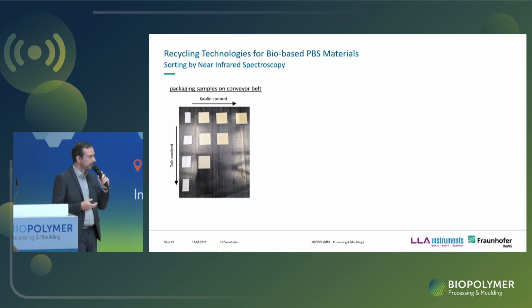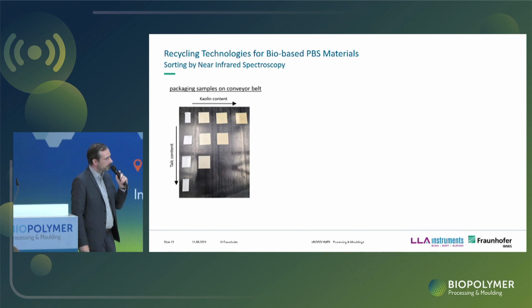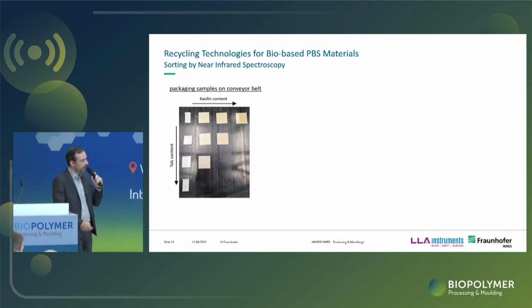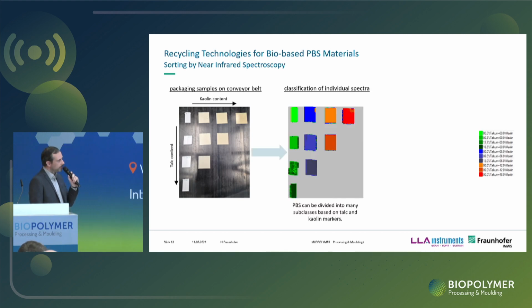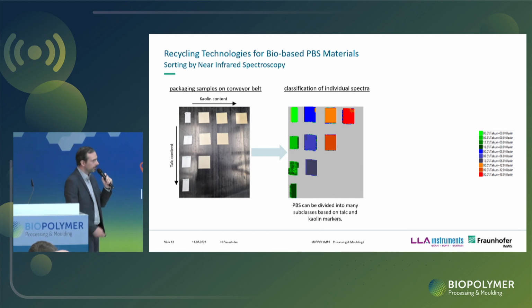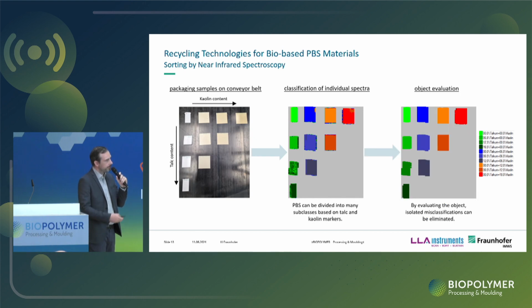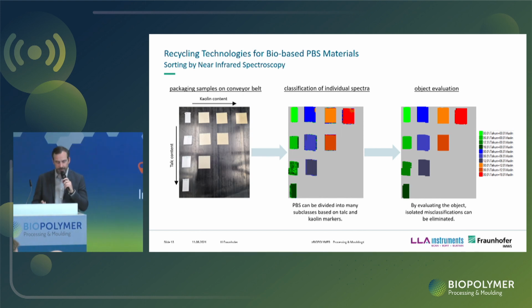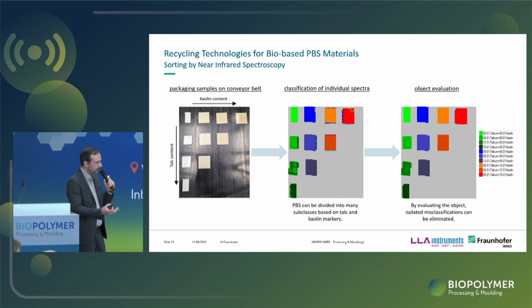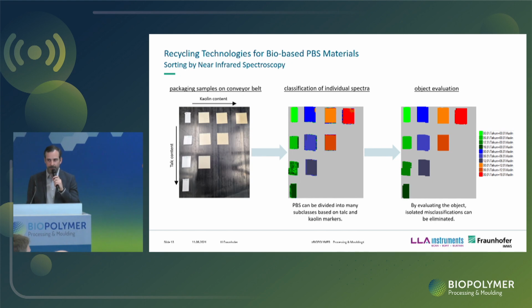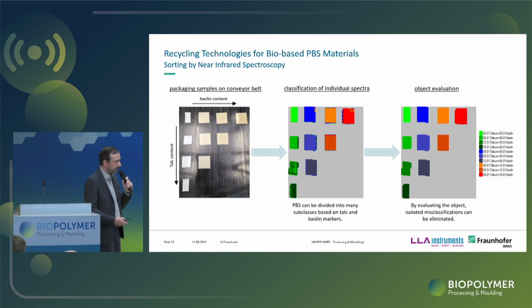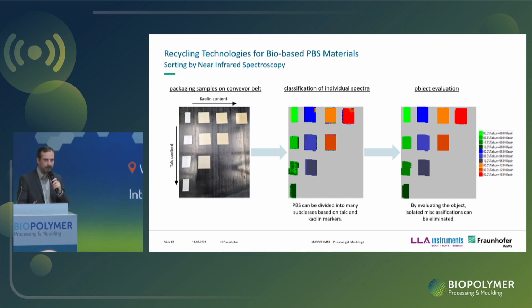So here you can see we made compounds of PBS with talc and kaolin with different contents. In the picture you can see on the top line the kaolin content is increasing, and downwards the talc content is increasing. And in the middle you have mixtures of talc and kaolin. So in total, you can make many different types of compounds, and you can detach many different types of materials at the end. This was clearly shown. Again, classification and then object evaluation. And in this example, we show that we can make 11, 12, or whatever, depending on the composition of the compound. You can make many different specific products which can be sorted out, and then each brand owner, for example, gets his own product back, and can recycle this material. This can be relevant for medical applications or specific food applications where really the brand owner needs his own material back.